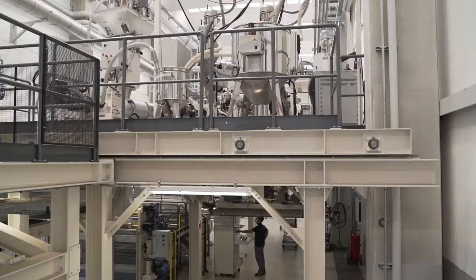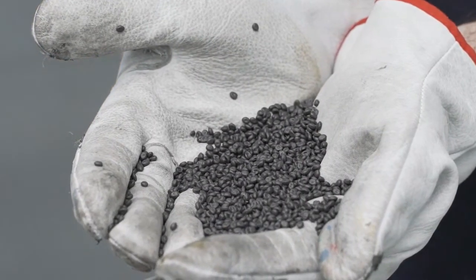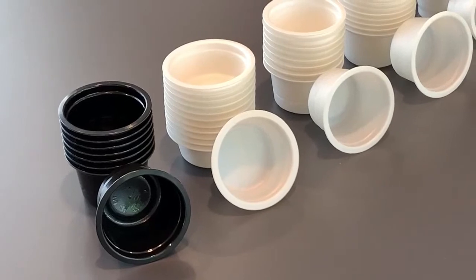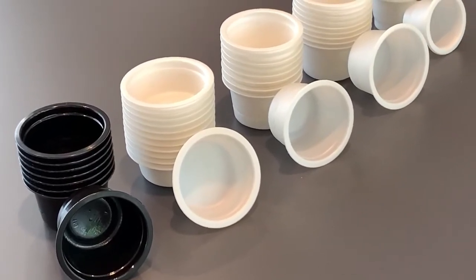By means of extrusion coating, Bandera can use high quantities of recycled material and thermoforming scraps in the substrate without any viscosity fluctuation issue, as opposed to the common co-extrusion in one die only. The production of compostable cups has become a market need. Coating line flexibility and the twin screw dryless technology offer the chance to process polypropylene and biopolymers independently. Allowing for thermoforming industrial scrap reuse, they provide for significant cost saving on recipe and a reduction of high biomaterial cost impact, with no degradation and keeping the virgin quality level.